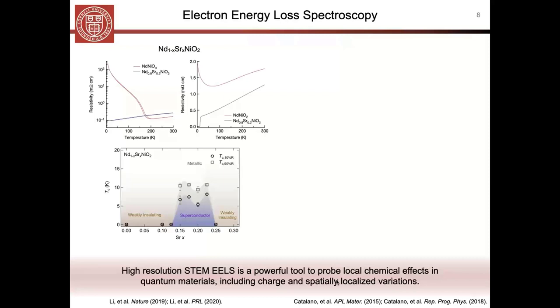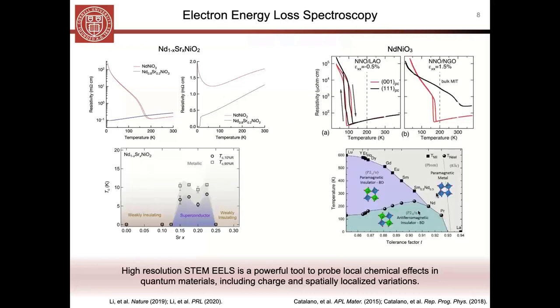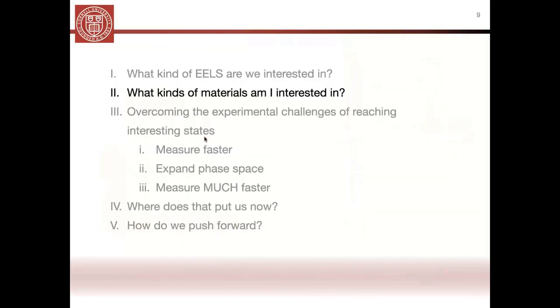Right, part of the problem is that even though we can do these local probes, if you look at the relevant phase diagrams that we might be interested in, what you'll notice is that the temperatures are intriguing, right? We typically measure under ambient conditions at 300 Kelvin. But if you look at these phase diagrams, for instance in the superconducting case, or even in the parent phase of these oxide materials that we're really interested in, you'll notice that the relevant temperatures are all below room temperature. Of course, there are some transitions that happen a little bit below room temperature, maybe 200 Kelvin, but there's a lot of really interesting things like superconductivity in particular that in many materials happens much, much lower, even below liquid nitrogen.